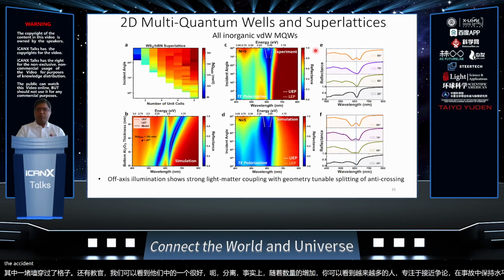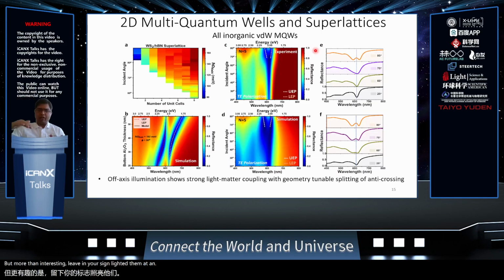But most interestingly, when you shine light at them at an angle, once again, this multi-layer structure traps the light into a waveguide mode, which ultimately couples to the exciton and splits into exciton-polaritons beyond a certain angle or incoming wave vector of coupling. Again, I should emphasize this is all at centimeter scale, room temperature, ambient conditions, normally seen only at cryogenic temperatures in other systems.